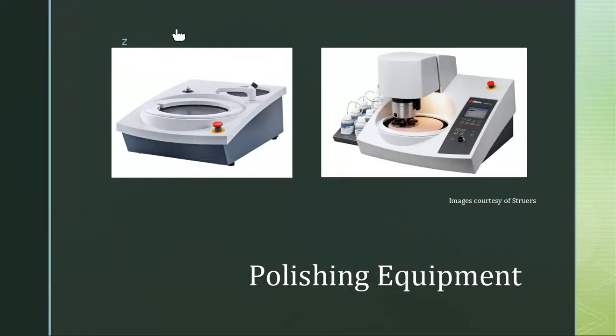If you're going to be grinding and polishing using the manual side, you've got to ensure that you clean the station between each step, especially when you get down to your finer micron sized abrasives. You cannot use this 9 micron wheel if you just did 600 grit and didn't clean it, because those particles somehow always find a way onto your pad.